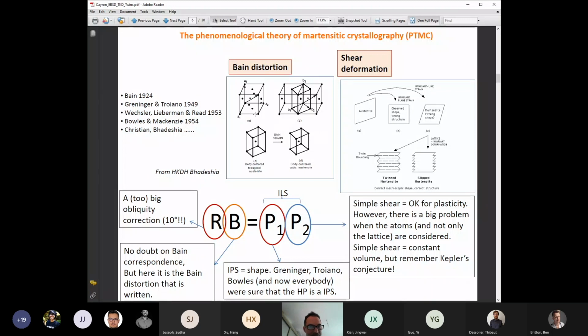Bain had this marvelous idea: look at this cell. You just have to contract one axis, the B3 axis, and extend the B1 and B2 axes to get a BCC structure. So this transformation is called the Bain distortion, and it is actually more specifically a stretch distortion.